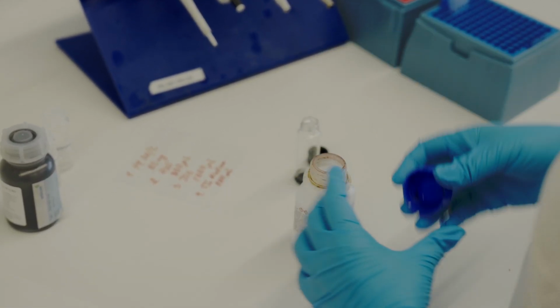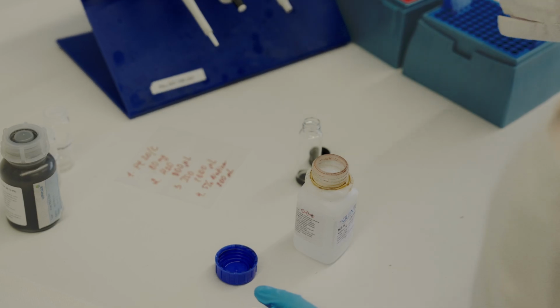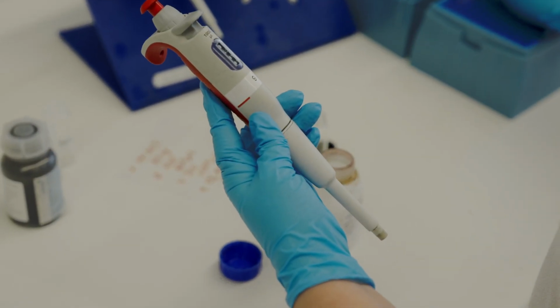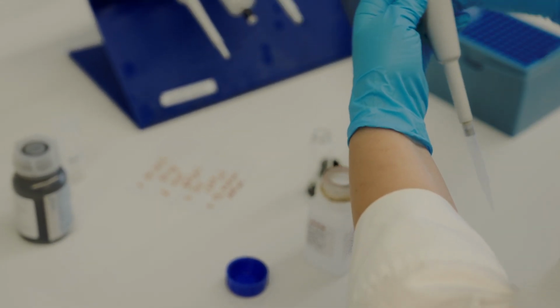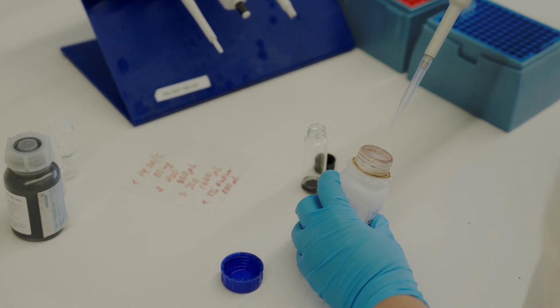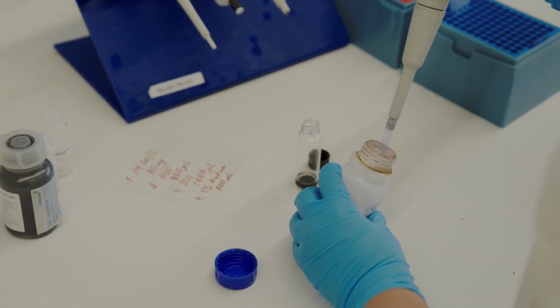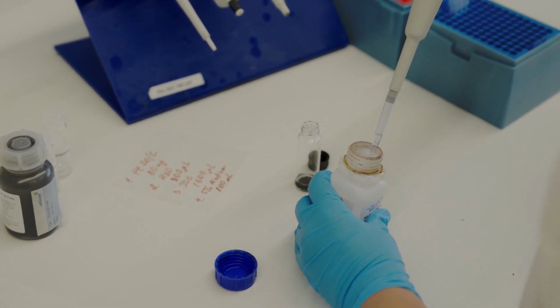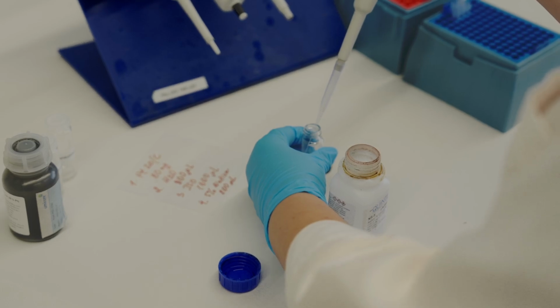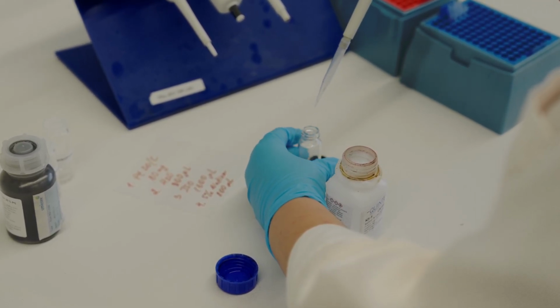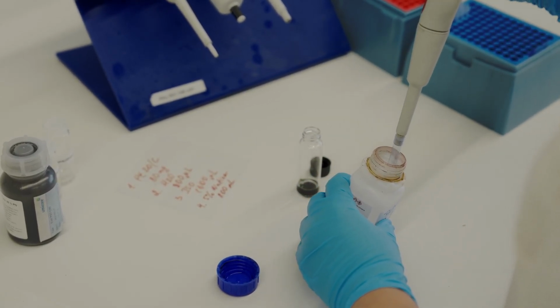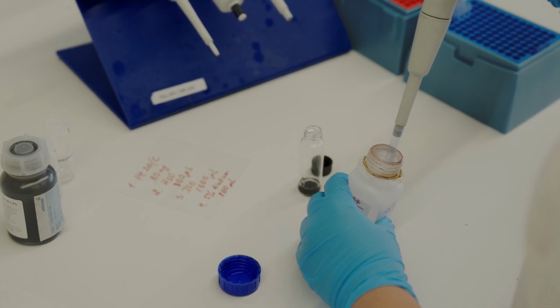In modern catalytic layers, the ratio of electrolyte to catalytic materials typically ranges from 1:1 to 1:3. That is 1 part electrolyte to 1 to 3 parts catalytic material, and these two components are mixed in appropriate proportion depending on the number of samples to be produced, accounting for losses during layer deposition.